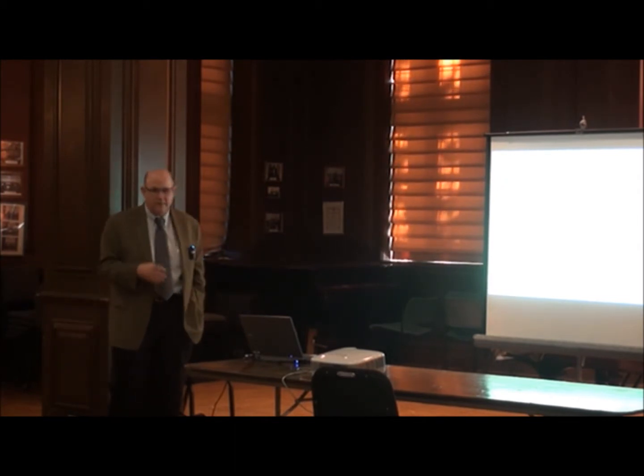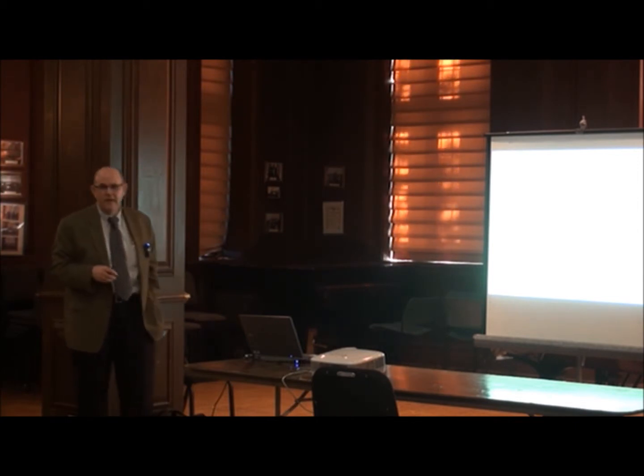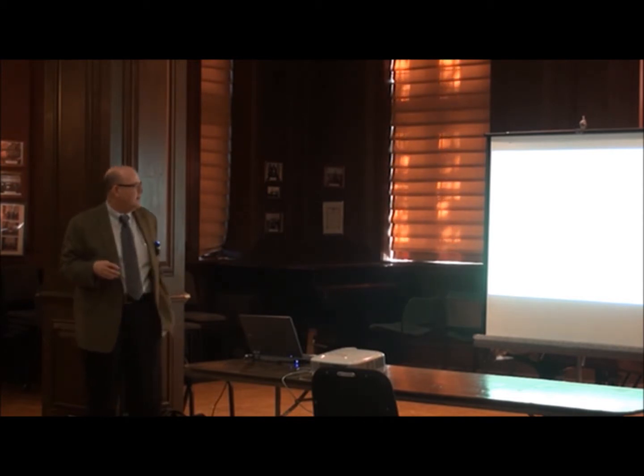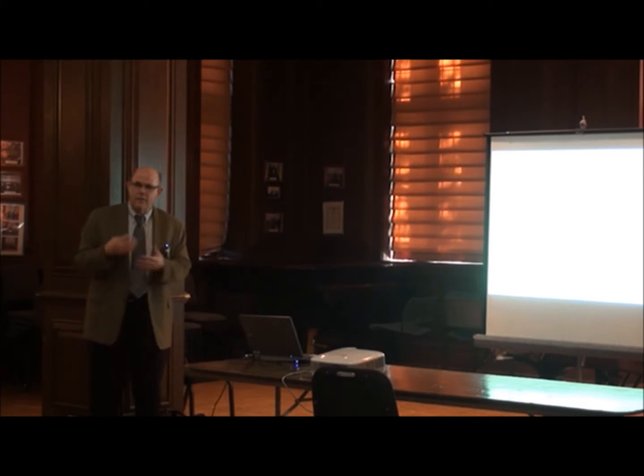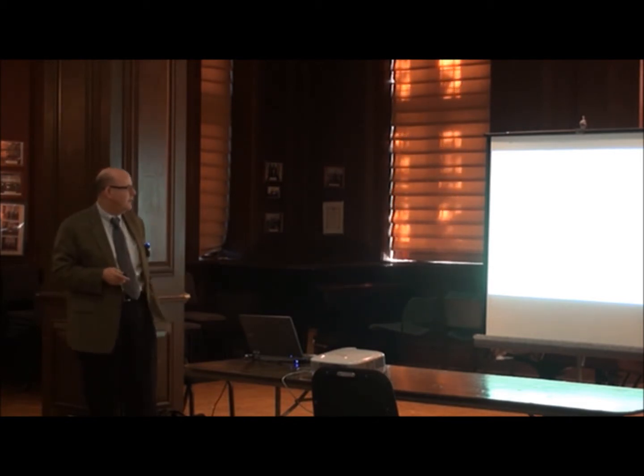But bear in mind, there are also losses due to plastic deformation of the asperities, side loading, plowing of one surface by the other. And even when you really dig into friction at the real nano level, we talk about elastic or phonon response. In other words, as one surface slides over another, we're causing lattices to vibrate, and they have hysteresis, and you lose energy that way as well. But that's the notion of this.